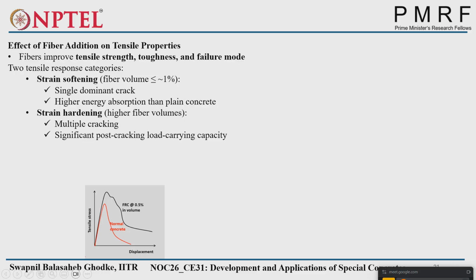So what effect does the addition have on the tensile properties? Fibers improve tensile strength. You see this graph of tensile stresses: this is the normal concrete, and this is only 0.5% volume fiber reinforced concrete, but the tensile stress is higher than normal concrete. So tensile strength increases, and toughness, the area under this curve, and failure mode also change. Strain softening happens if fiber volume is less than 1%: a single dominant crack, with higher energy absorption than plain concrete. Strain hardening occurs at higher fiber volumes, more than 1% or more than 2%. Multiple cracking, as we saw in the last image also, and significant post-cracking load carrying capacity. Both are greater than normal concrete.